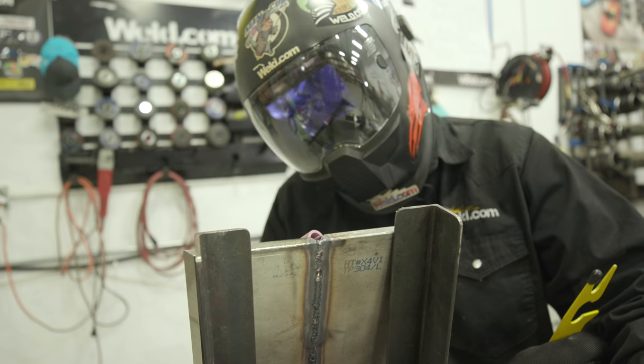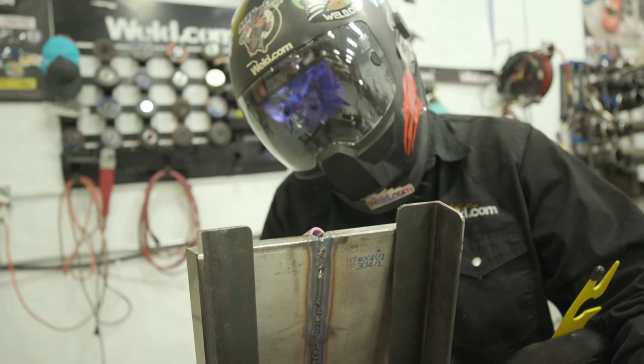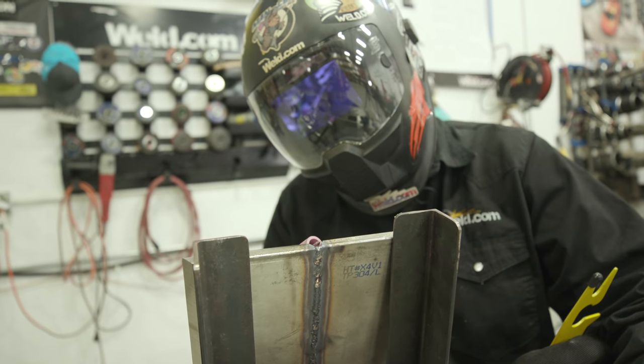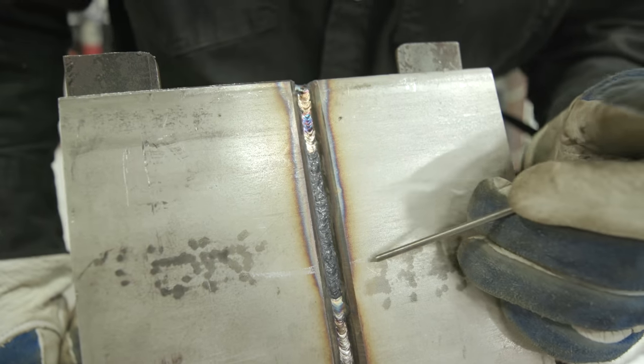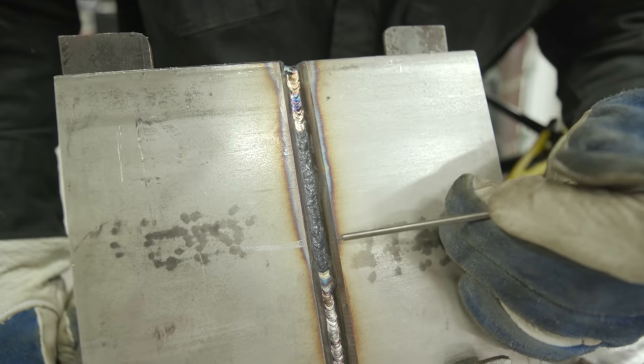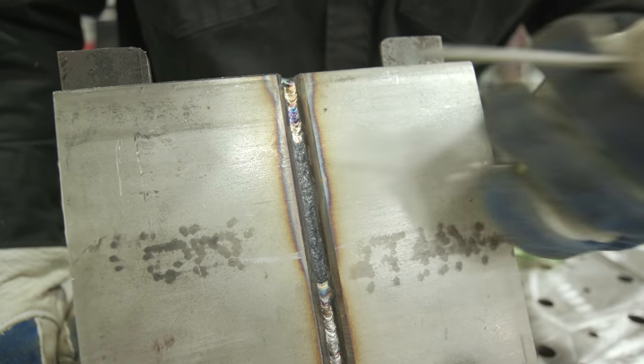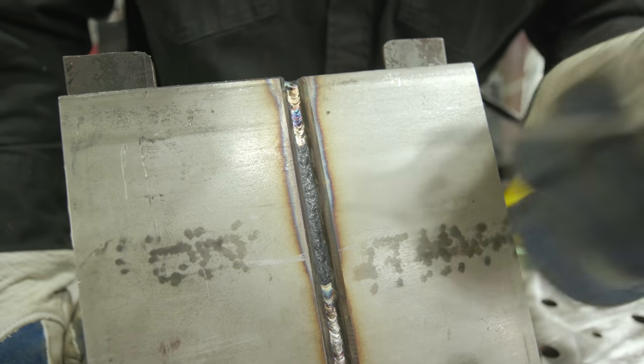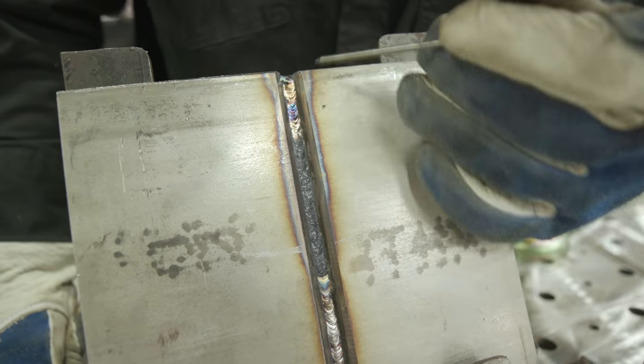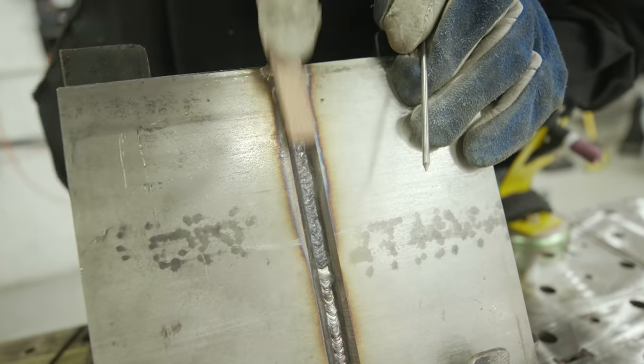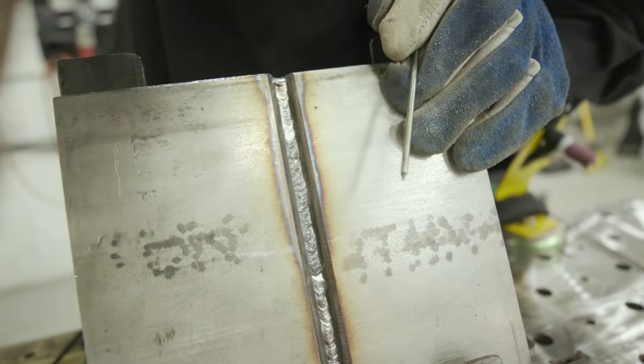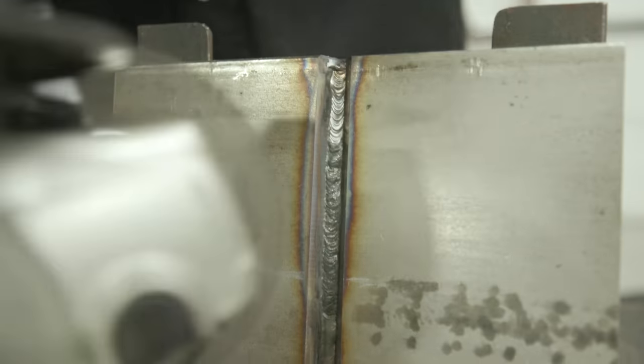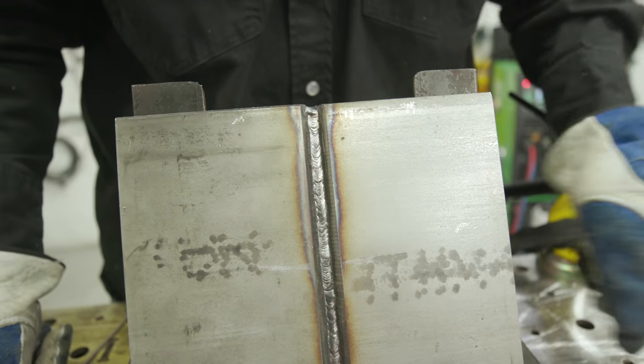We're gonna come over off onto the bevel, the thick part, and slowly release our amps and break away. See how I'm not taking my cup away yet? I'm letting that argon cool all that down first, keeping the atmosphere away from it. You hear my gas go out, now I pull away. This is not really gray like you would see normally when you're running 308 stainless.